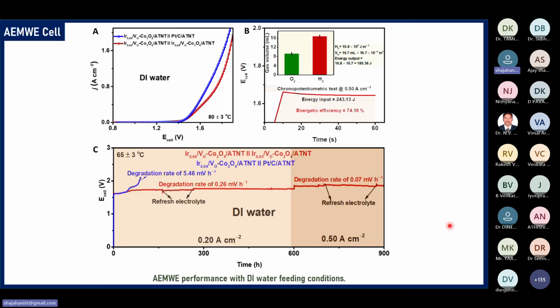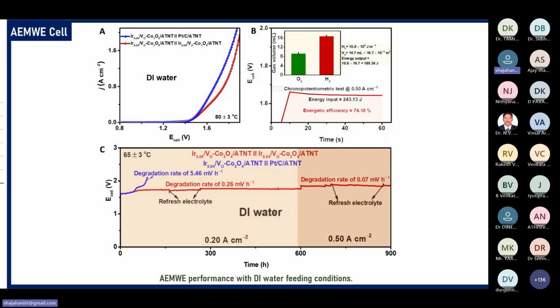With the DI water, it is almost 900 hours. 900 hours. It is very high with the DI water. If you use the same catalyst on both sides, it is maintaining 900 hours. It is very good. Performance also, it is almost reaching 1.6 at 1.8. Energetic efficiency, from 69 to 74.18% we increased with this advanced catalyst with the DI water feeding. So this is actually a positive result for hydrogen production.